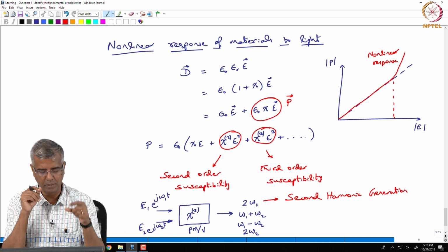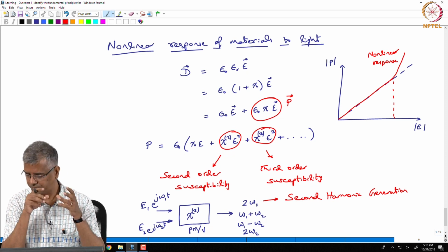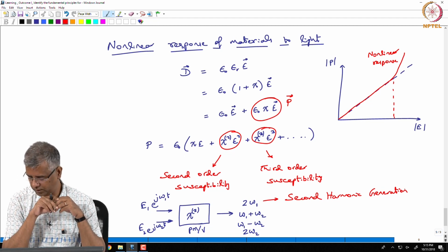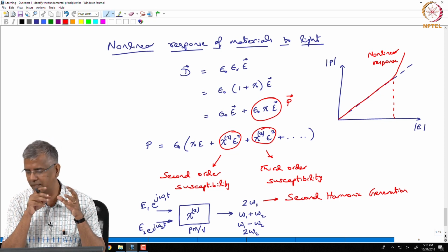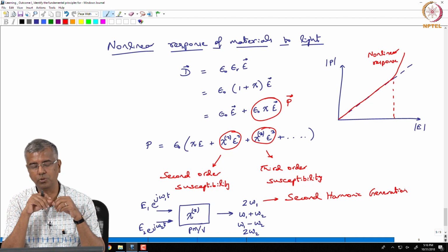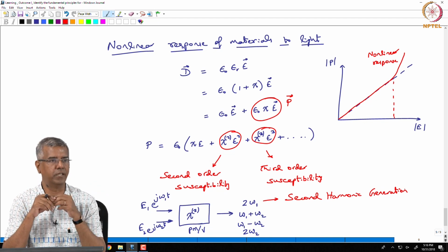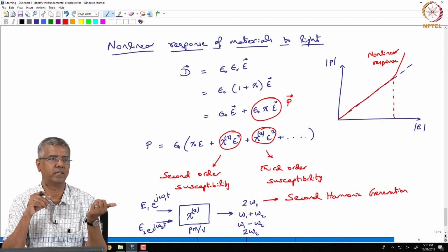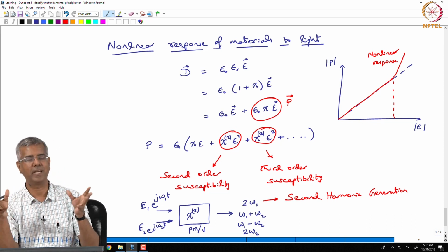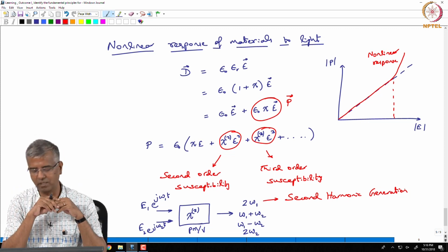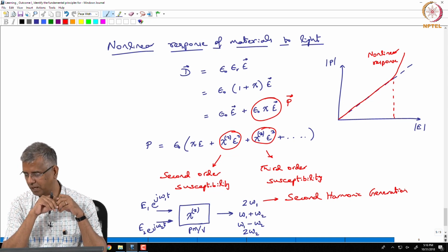and that output is made to pass through a crystal, right. KTP is one crystal, potassium... What does KTP stand for? Does not matter. So, there are crystals which have a large value of χ2. So, you send it through one of those crystals, then from 1064 you can get 532 nanometers, and that is the green laser that you see from a green laser pointer. It is not like a green semiconductor laser that is emitting that. Okay, that is actually, you know, a very good example for second harmonic generation.